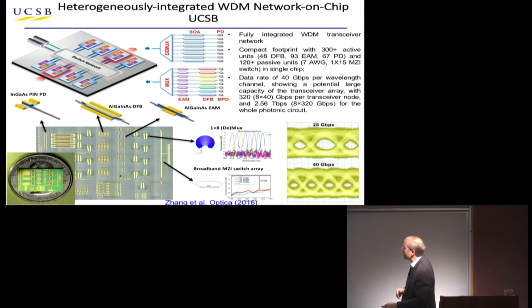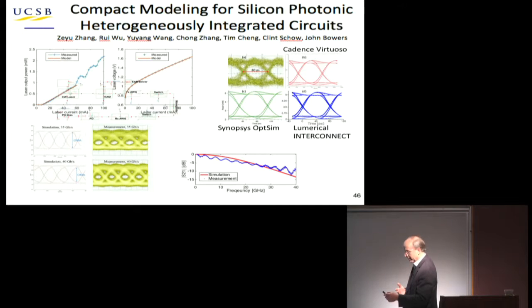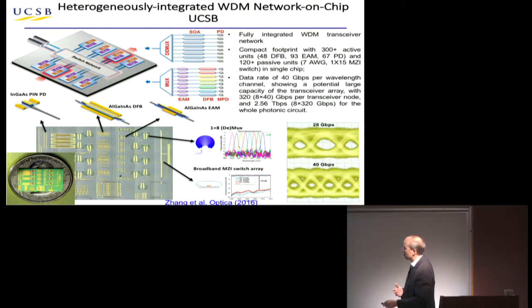So you put in light from the laser here, and different delay lines across here. They all get combined, and then out of each of these ports comes a different wavelength. So on a DEMUX, you have a different detector for each channel here. Going back, this spacing is quite close, just a few hundred gigahertz. And so if we have 2 sidebands, each taking, say, 50 gigahertz, there's not much room in there for any roll-off in that performance. And you can see here, this is not a flat-top AWG. Now, other people designed flatter-top AWGs, which would work better. But for what we have here, that ends up being a limit.